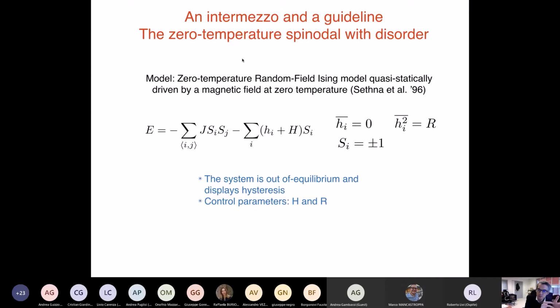So the magnetization will start at -1, and then when the field H is very, very strong, the magnetization will go to +1. But we want to see whether or not there is a phase transition in between. So the model is defined, just to recall to you here: the energy has a short-range ferromagnetic interaction between Ising spins S_i, where S_i is equal to ±1. And then there is a random field coupled to the spin S_i, which is h_i, which has a 0 average and variance R. This R is the strength of the randomness in the random field. And then there is the external magnetic field H.